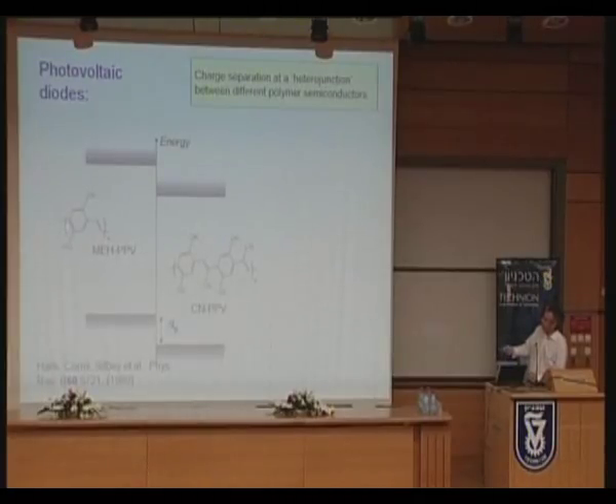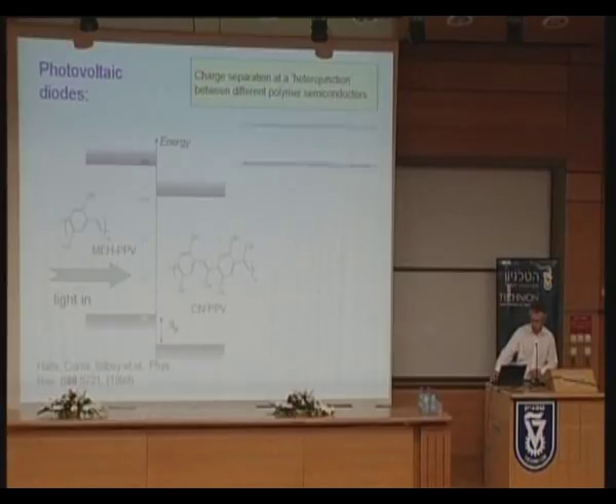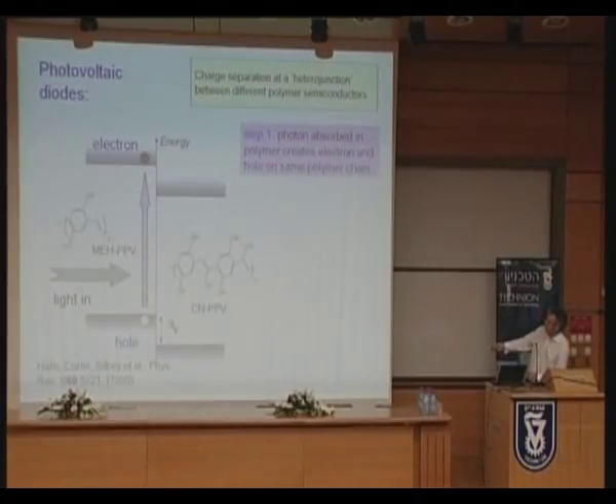Now, what's illustrated here are two different forms of this polyparaphenylene vinylene backbone. One with alkoxy side groups, which makes it soluble, and the other here with cyanide groups attached to the vinylene carbons. The cyanide groups are electron withdrawing. What they've done is to pull down the energy of the lowest pi star conduction band state and the top of the valence band pi state with respect to the polymer without the cyanide groups. Now, if we can arrange that those two materials are next to one another, then the process that we want to make work is that we absorb a photon, which lifts an electron up from the pi state to the pi star state in the left-hand polymer chain.